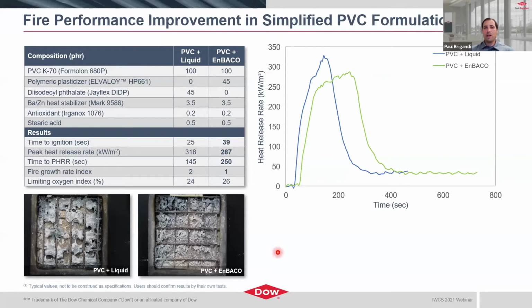One thing I'll point out is the limiting oxygen index. Not a big difference, right? We don't see a huge difference in LOI. And that's to be expected, as that's a property that's often used, but also often dictated by the formulation itself.